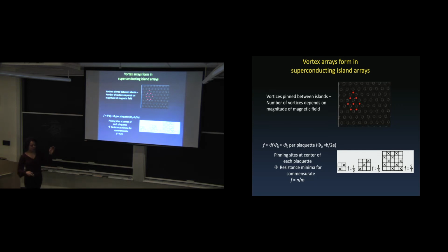So if I take my magnetic field and divide it by the number of flux quanta, I get 1/2. Okay, and that's something like this. And so we call this a frustration of 1/2. It's the amount of flux per flux quanta. If it's a 1/2, it means that we have a flux quanta in every other plaquette. If it's 1/3, it means we have a flux quanta in every third plaquette.